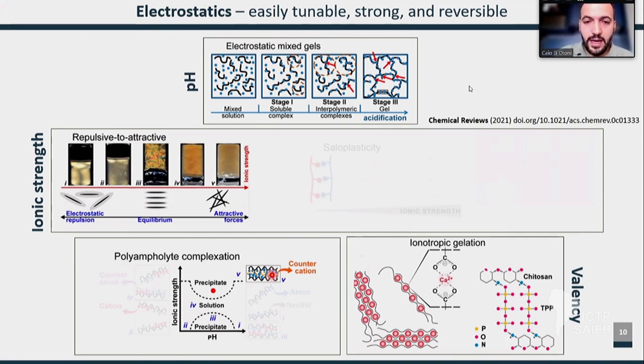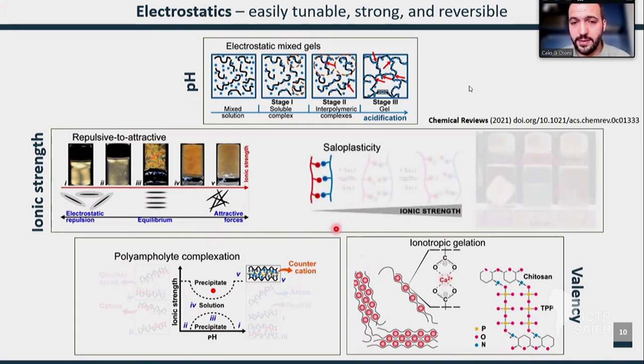Sorry. The other case that I like is what we call the saloplasticity. If you have heard about materials processing, there are thermoplastic materials that flow upon temperature and shear. So what temperature does to the thermoplastics for recycling, for processing, is the same that salt does for the saloplastics, right? So at low ionic strengths, you can see that the polycation compensates the charges of the polyanion and vice versa, right? So the charges are always compensated. This is what we call the intrinsic charge compensation. As we put salt, you see it's both ways, right? So you can put and remove salt.